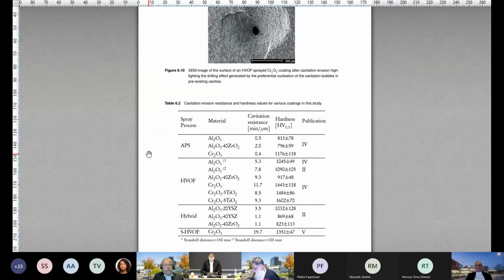Well, in the case of cavitation, I believe it comes to scale, because the splats are smaller than with plasma spraying. They essentially are the same size or slightly larger than the cavitating bubbles. And if there is some splats that are detached, it's a small splat that leaves a small dent. That's not a big incubation site. Whereas with the plasma coatings, you have big splats that are well adhered because they're well molten. And the cavitation kind of drills one piece around and it becomes a site for the next bubble. So there was a big difference between them here.